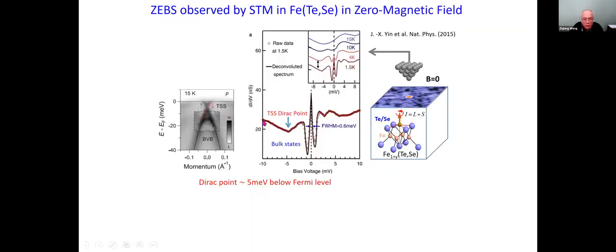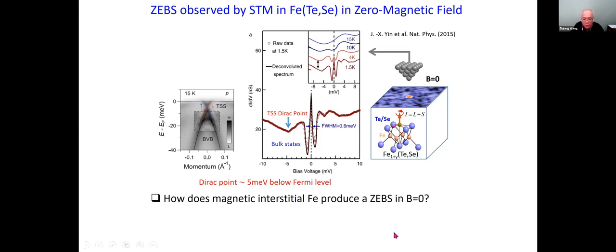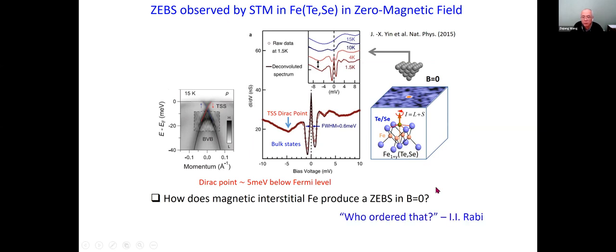The V-shaped density of states seen down to about minus 5 meV is completely consistent with ARPES finding a Dirac crossing about 5 meV below the Fermi level. So what is seen here is indeed a superconducting topological surface state. But how would we have a zero bias peak or zero energy bound state in zero magnetic field? This reminds us of the famous Rabi quote when the muon was discovered: 'Who ordered that?' And in particular, is this really a bona fide Majorana zero mode?